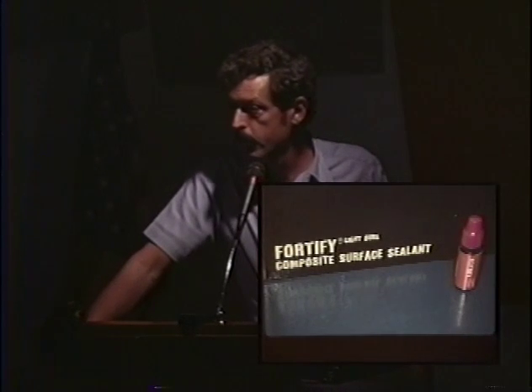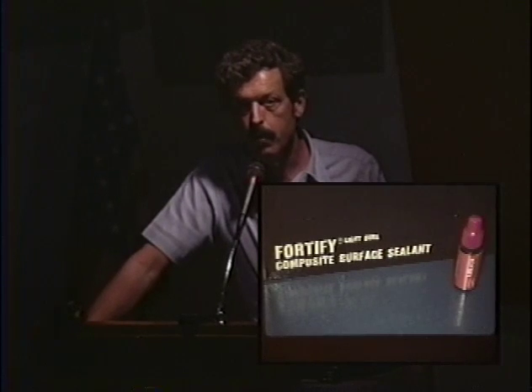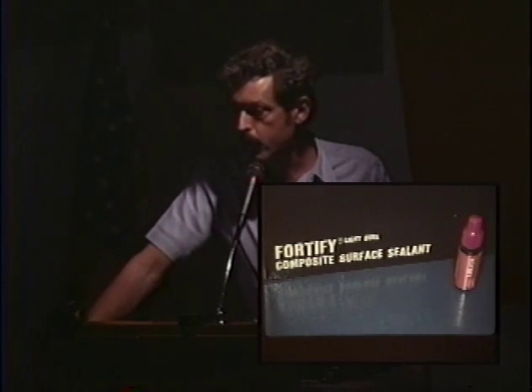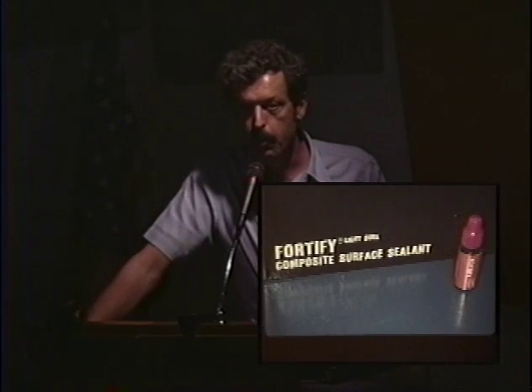This is an unfilled sealant, yeah. If it's filled, it wouldn't penetrate that defect. Furthermore, it's a low viscosity unfilled sealant. It's not BIS-GMA. BIS-GMA or TEGDMA or HEMA is too thick. This is urethane dimethacrylate with a solvent in it, most likely alcohol, although I don't know what's in it exactly. But it's urethane dimethacrylate based. Makes it water thin.